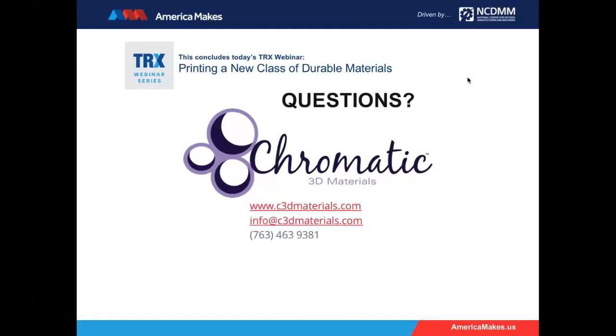Okay, thank you. The other one that came through says, how long does it take polyurethane layer to cure before it can be printed on top of? Okay. This is something that we can actually tailor. We typically design our parts so that you can lay something on top of it within about 20 seconds. So it's, for a large part, that's usually not a problem at all.